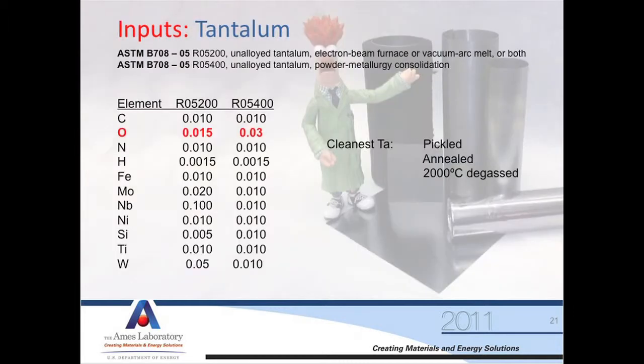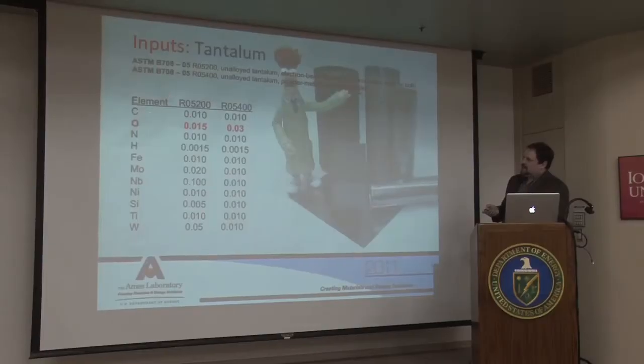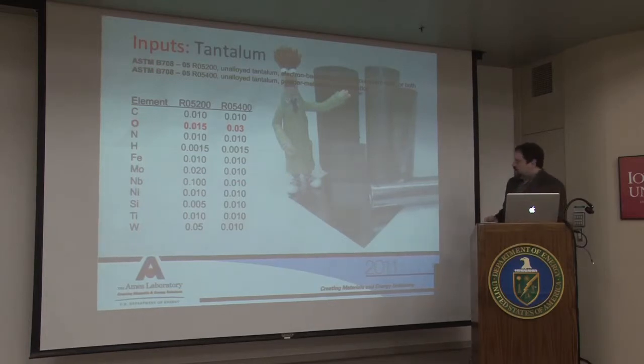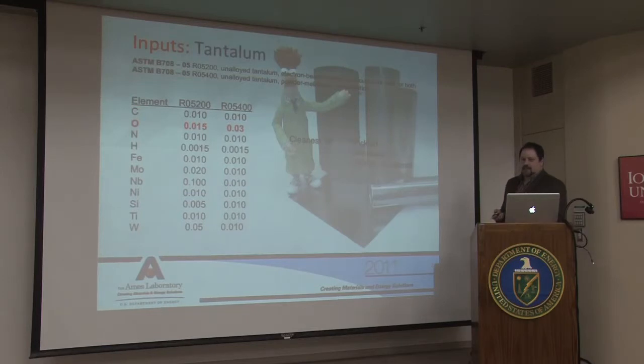But tantalum may be a source of impurities. According to the ASTM standards for making tantalum — whether through powder metallurgy processing or electron beam or vacuum arc remelting — there's a little bit of oxygen in it, a little higher for the powder metallurgy version. Iron is a concern; if there's a lot of iron in it, it might carry over into our metal. However, the tantalum of today versus 20 years ago is a lot better, so we're not as concerned. If you really want clean tantalum, you pickle or acid etch it, then anneal or degas it at high temperature to clean up the material.